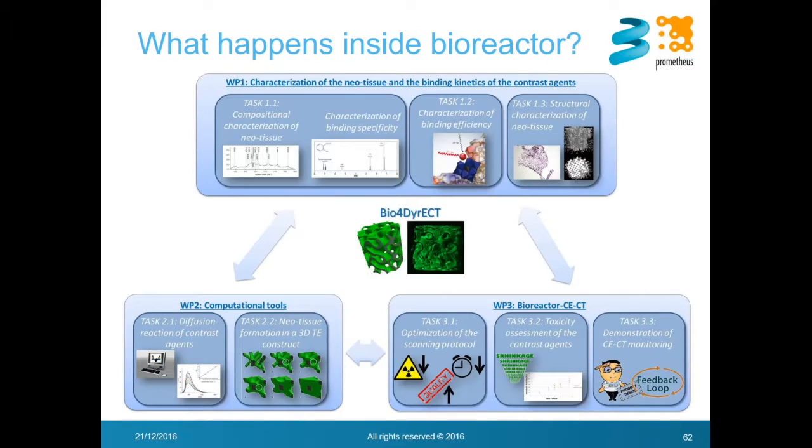And then we're also developing nano-CT imaging so that we can also image online what is going on inside the scaffold, even though it's a titanium scaffold. But using contrast-enhancing agents, we can actually also image the soft tissues during culture without the need to remove the scaffold from the bioreactor.